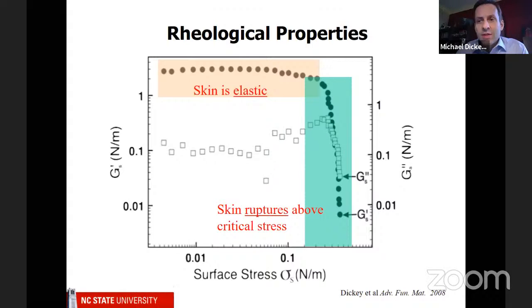And so what we have found is that we generally treat this oxide layer sort of like surface tension, in the sense that if you have a droplet of liquid and you try to make it bigger, you're going to be opposed by surface tension, which is like a membrane on the outside of a liquid. And so we've generally found that in terms of the pressure response of this material, you could just treat it like Laplace pressure, which is just to say it's very much like surface tension. The difference, I'm a little reluctant to say that because that's only true in tension when you're trying to expand the droplet. When you try to recede it, it's a different story.